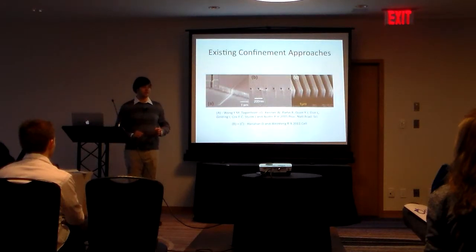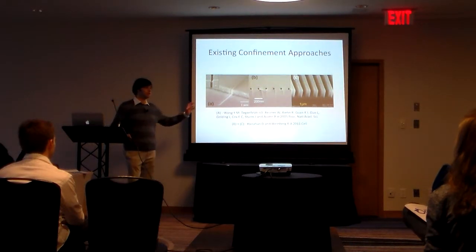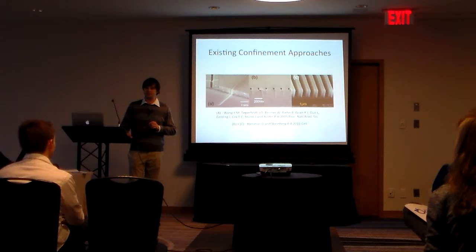One existing approach to this is the use of these nanochannels, or nanoholes. Via the use of electron beam lithography, you're able to produce these features in fused silica substrates as small as 20 nanometers in cross-section. There are, however, some limitations to this approach.